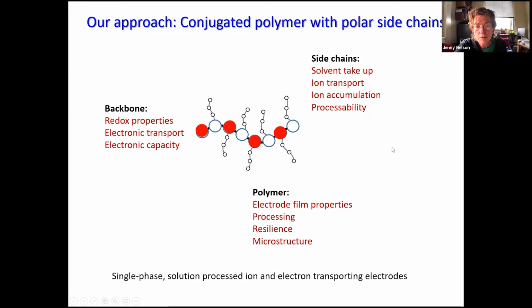They would be responsible for controlling the take-up and transport of ions, and for the interaction with the solvent. And then the properties of the polymer as a whole, its molecular weight, its crystallinity, and so on, would control the properties of the electrode film, how easy it is to process, its microstructure, and how resilient it is under the interaction with the electrolyte during charging. The goal is then to have a solution processed electrode with mixed conductive properties, that can be cast as a single phase.